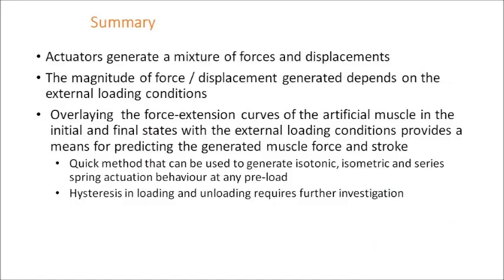In summary, we recognize that all actuators generate both forces and displacement, and we have seen that the magnitude of both depends on the external loading conditions. It would be nice to have a simple method to estimate the actuation force and displacement for all possible loading conditions. Traditional tests generally use the approach of choosing the external loading conditions such as isotonic, isometric, and so on. We've found that by measuring the force extension curves in the initial and final states and overlaying them on the same set of axes, we have a graphical method for determining actuation against isotonic, isometric, and spring-series loading. In fact, the actuation could be estimated using this method for any external loading conditions. Complications were noted due to hysteresis and training effects in some of the samples, and these require further investigation.